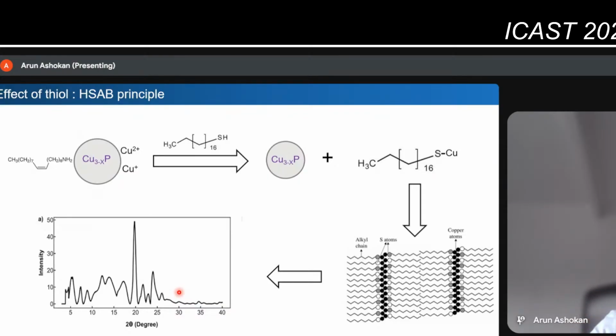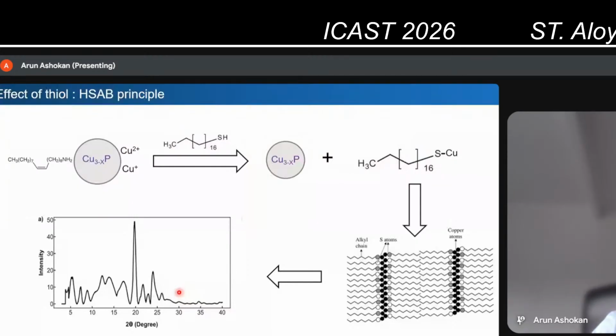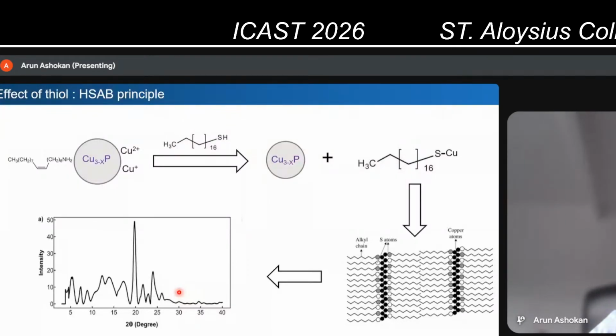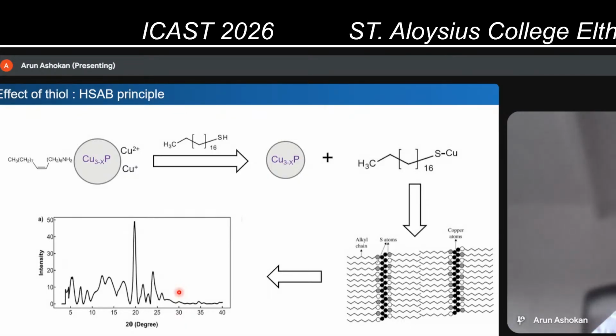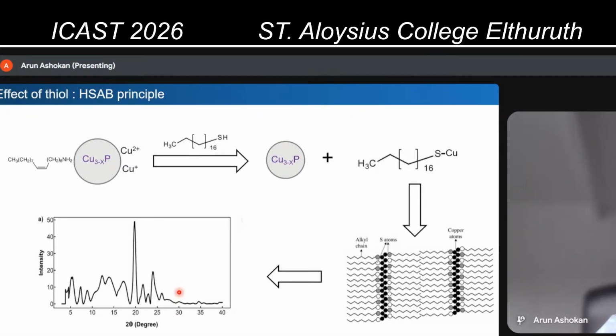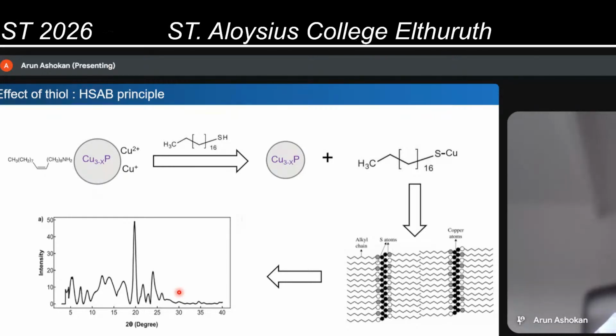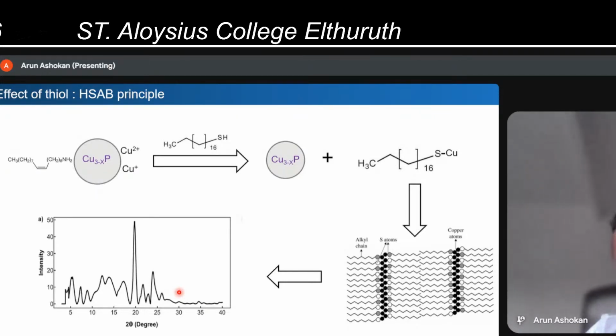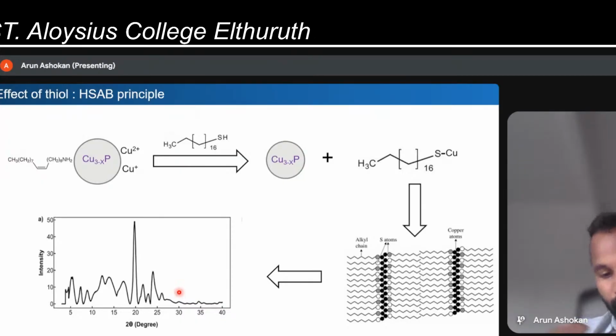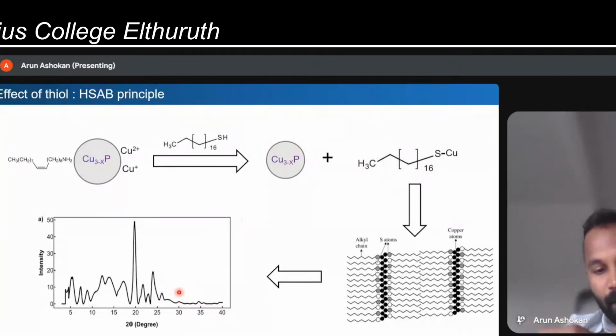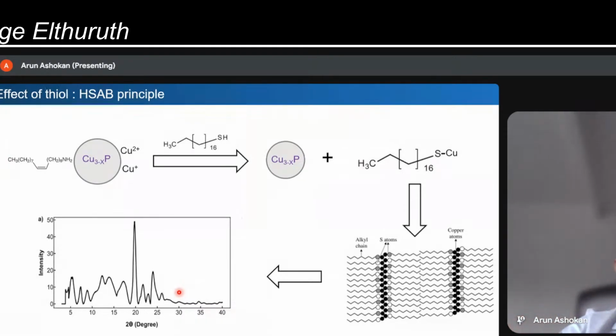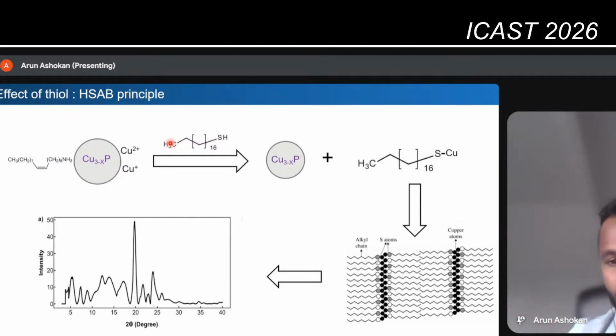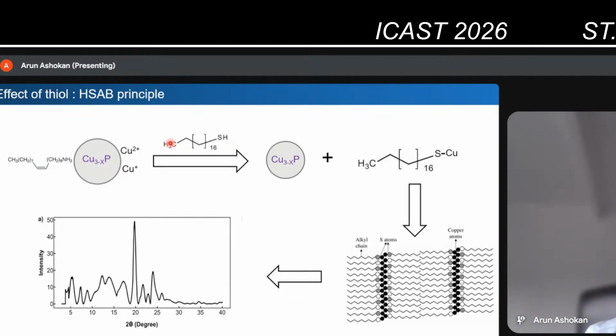The reason is because when you make these nanocrystals, ultimately you want to make devices. In these devices, when the nanocrystals are separate, the response or the charging will be slower. If you want to increase the charge transport between the nanocrystals, you want to cross-link them. So basically, what scientists have used so far is ligands with two donors. In the case of a monothiol used here, they basically use a dithiol, another thiol here. So it will cross-link the nanocrystals, and the response will be better and faster.